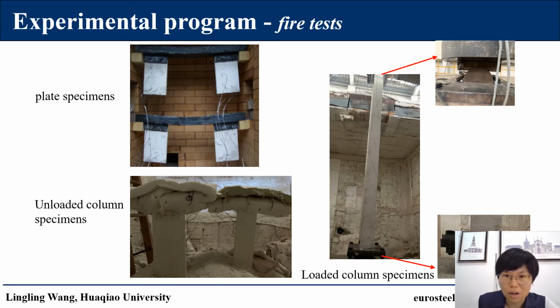In all tests, the furnace temperature was regulated according to the ISO 834 standard temperature-time relationship. The actual deformation and temperature were measured and recorded continuously. Fire tests on loaded specimens were terminated when the axial deformation or deformation rate reached their limits. Fire tests on unloaded test specimens continued until the average steel temperature reached 700 degrees centigrade.